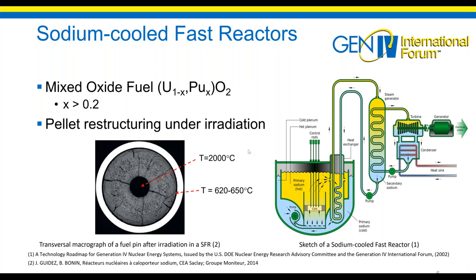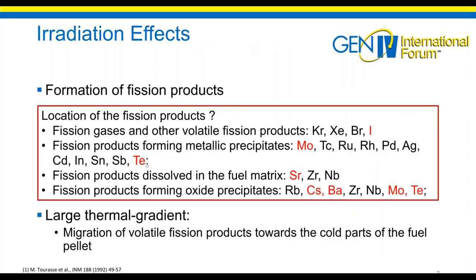I was talking about a fuel pellet, but this design of reactor uses mixed oxide fuel, U(1-x)Pu(x)O2, with a plutonium content between 20 and 30 weight percent of plutonium. Under irradiation, the fission of these heavy atoms will release energy and create what we call fission products, compounds of fission products. Moreover, during this irradiation, there will be a restructuring of the pellets, as we can see here, for example, with the formation of a hole in the middle or some cracks over there in the whole pellets. And this will have an effect.